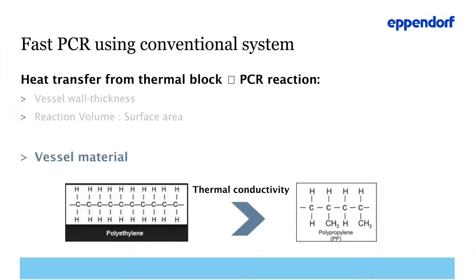Recently, another innovative strategy was developed, that is to attack the root of the problem itself, which is heat transfer. If special format is not desirable, then we keep the existing shape. And if polypropylene is fragile and cannot get thinner, then we keep the same thickness and use another material that has higher thermal conductivity. And the polymer that fits this characteristic is polyethylene. It is as malleable as polypropylene, but has a much higher thermal conductivity than polypropylene. Hence, it is able to transfer heat faster from the thermal block to the PCR reaction mix.